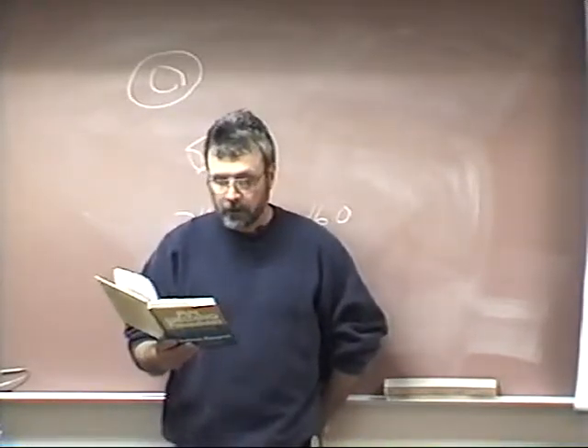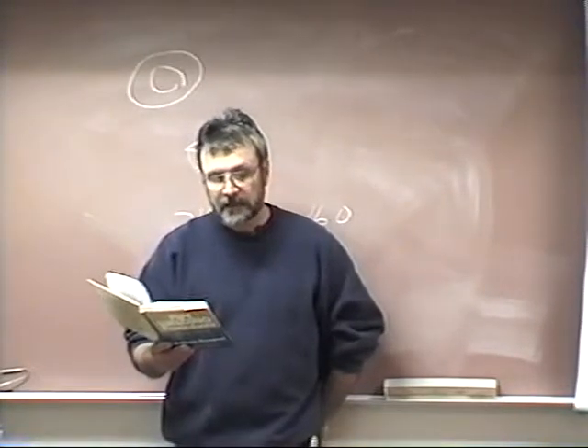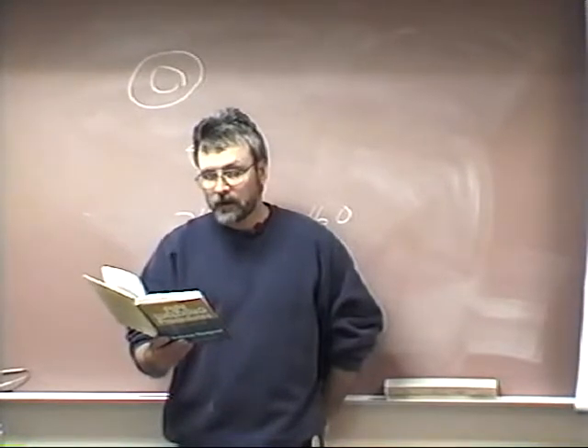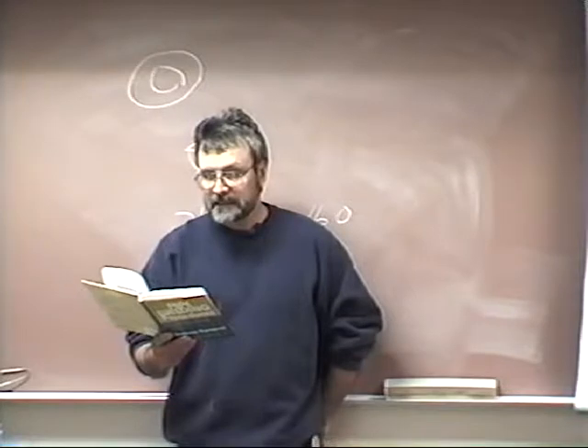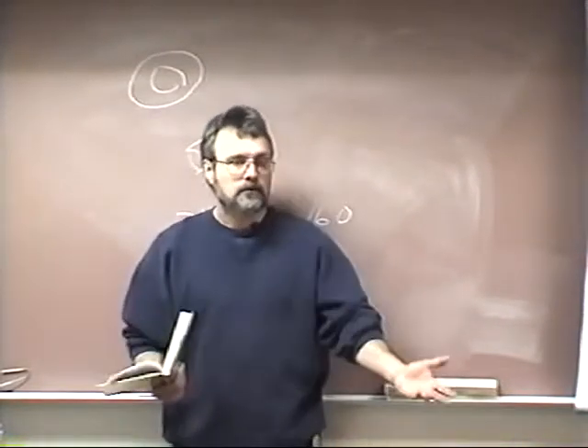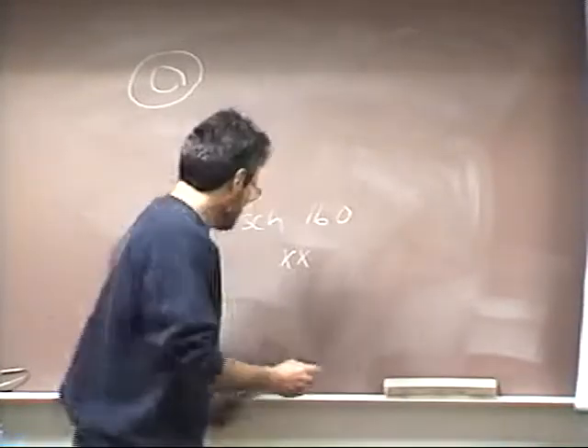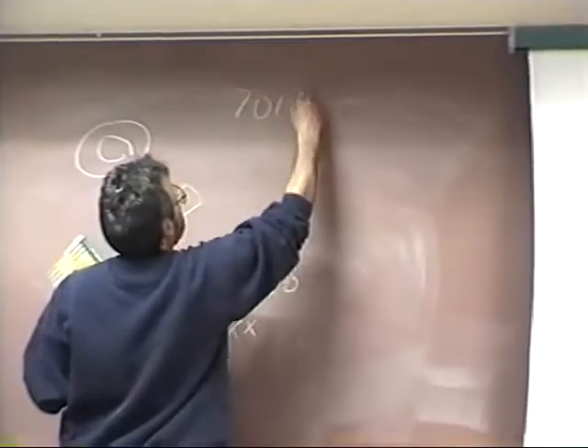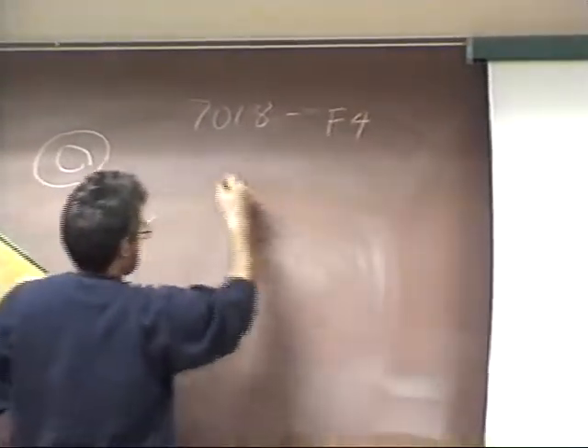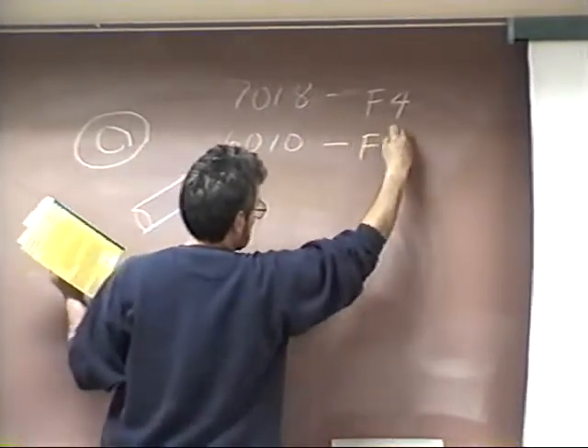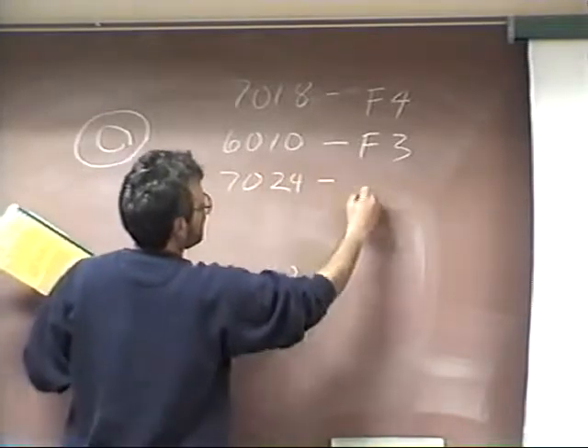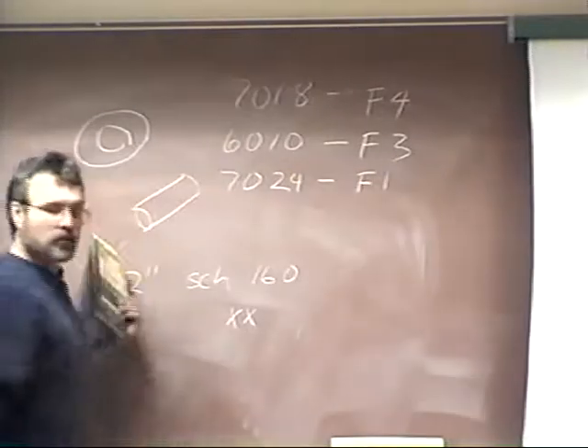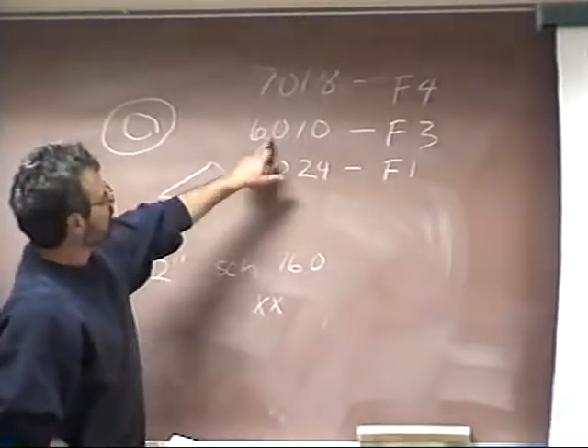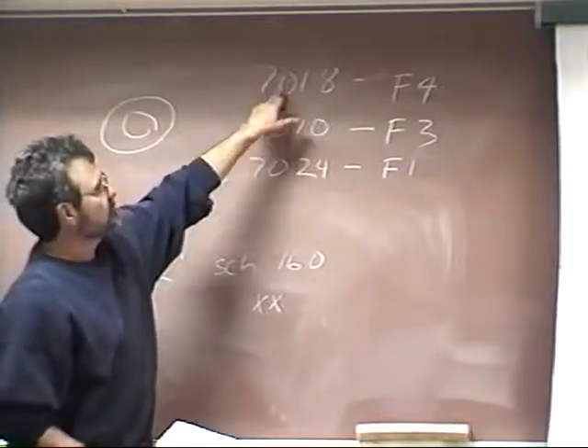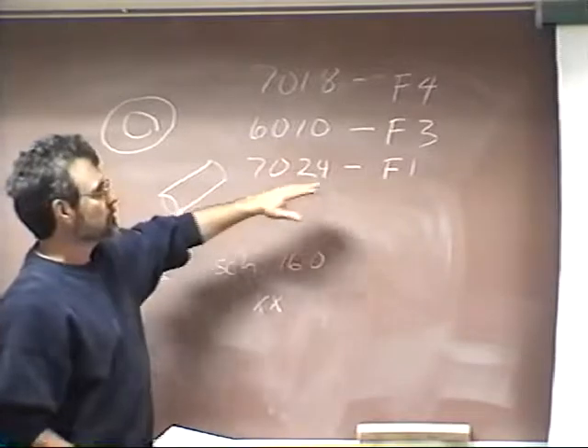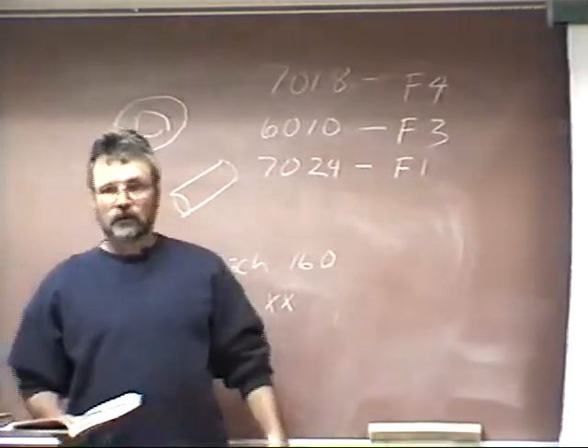Another example, an operator who is qualified with an E6010 is not necessarily permitted to use a low hydrogen electrode. If he is qualified with a low hydrogen electrode, it is possible for him to use an E6010 if the job permits. What's a low hydrogen electrode? A 7018. Well, the difference there is 7018 has an F number of 4. 6010 has an F number of 3. 7024 has an F number of, I believe it's a 1. It's either a 1 or a 2. So if you're qualified on this, you could weld 6010 and 7024, but not 7018. If you're qualified on 7018, you could weld either of these. The higher the F number, the more you're qualified to weld those underneath that.